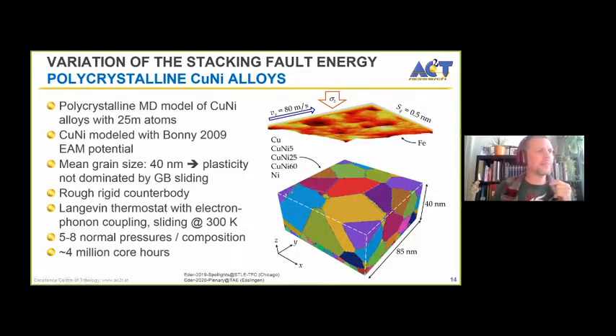So here's a system that we're not going to grind on, but that we're actually going to slide upon. And this is a study in alloys. So we have copper, we have pure nickel, and we have 3 alloys in between. And we're going to change the stacking fault energy by changing the alloying between these 2 metals. And then we're going to press a rough iron surface against it and start rubbing.